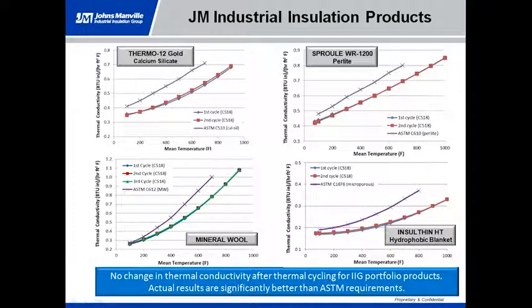And what we saw is that there are some very slight changes, as you can see with the Thermo-12 Gold calcium silicate product, and maybe a little bit with the Insulthin HT product, but generally speaking, those differences are very small, and one could argue that those are within the uncertainty of the test method. But I think it's fair to say those results are equivalent. There's no real change in the thermal performance of these products, and they perform significantly better than what their ASTM standard specification requires.